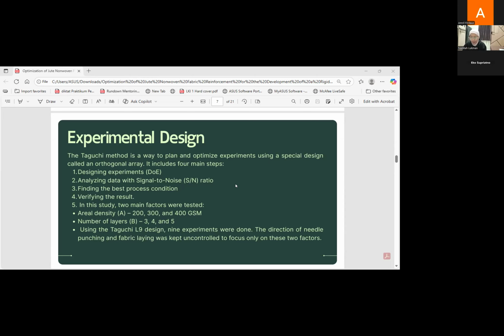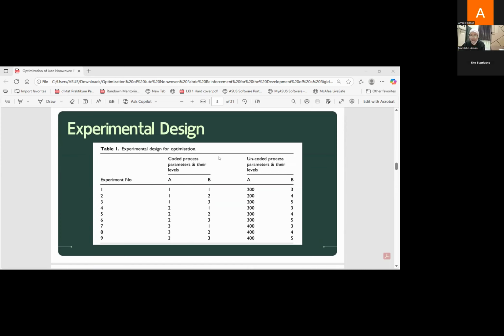In this paper, areal density was varied at 200, 300, and 400 GSM, with 3 layers, 4 layers, and 5 layers. Using the Taguchi method, this is called the Taguchi L9 design. 9 experiments were done. The direction of the needle punching and the fabric laying was kept uncontrolled to focus only on these 2 factors. So this is the table of the experiments with the Taguchi L9. This is the sample number, and this is the process code. A is the areal density or grammage, and B is the layering, how many layers the composite has. So for experiment number 1, it has grammage 200 with 3 layers.